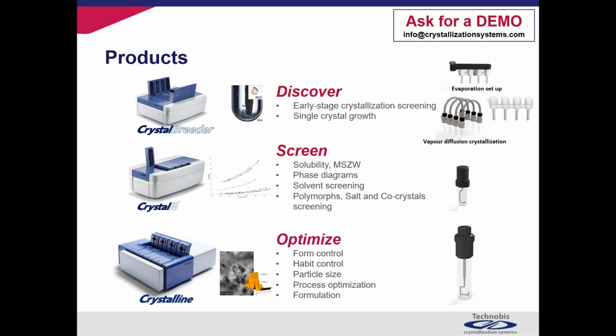On the other side, the Crystal 16 is your instrument for solubility determination, temperature-dependent solubility. In 4 hours, you can determine the temperature-dependent solubility curve of your compound. And not only that, you also have information about the metastable zone width and the supersaturation curve. Any type of induction time measurements, nucleation rates, you name it, it is possible to perform on this instrument. Polymorph, salt, co-crystallization type of screening, even amorphous solid dispersions you can perform on this instrument.